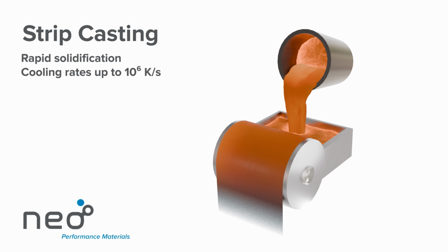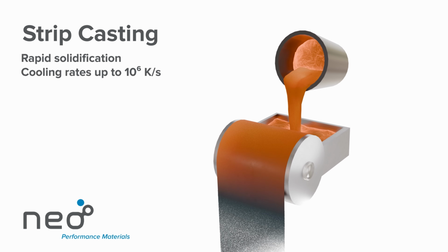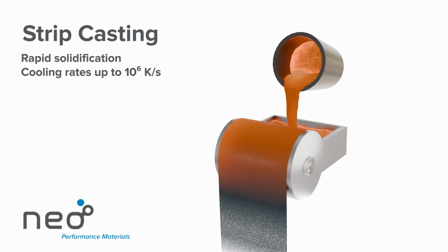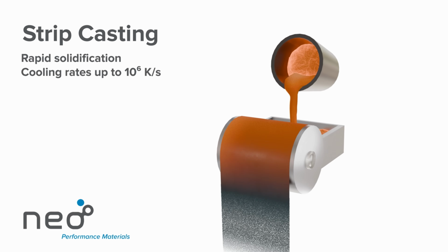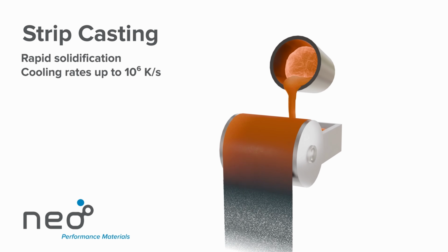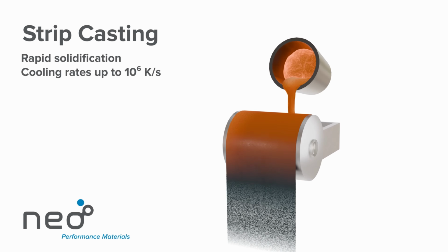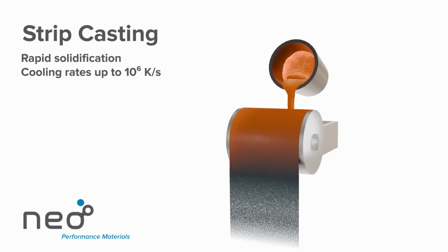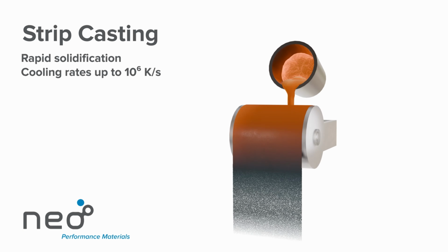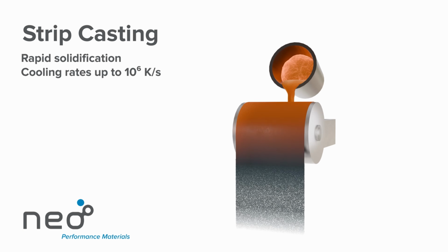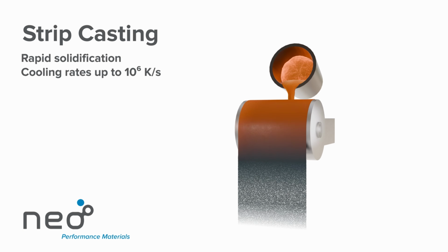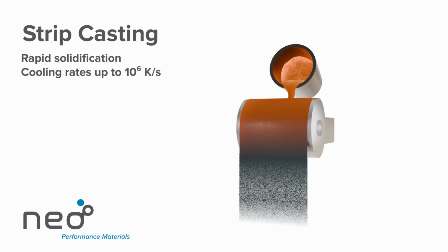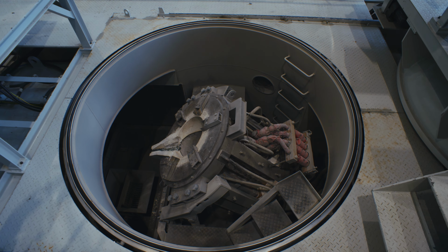The molten neodymium iron-boron alloy is poured from the crucible into a tundish. The molten alloy exits the tundish and contacts the surface of the rotating copper wheel. On contact, the molten alloy is instantly quenched and solidifies into thin flakes. Cooling rates exceed 100,000 to 1 million Kelvin per second, refining the microstructure and minimizing segregation.